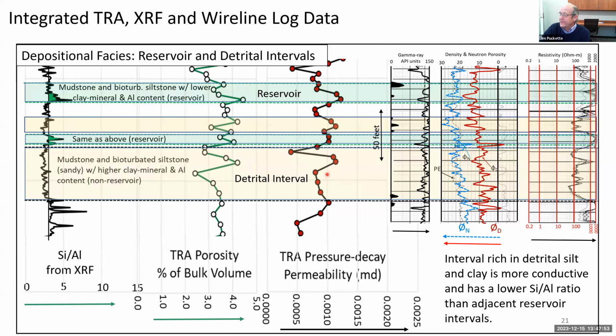And we see some pretty good porosity here at 4%. We see some pretty decent permeability in this rock. Our neutron and density curves aren't trying to really go towards each other, but they're not separating either. And our resistivity, well, in certain intervals here, it's getting up close to 1,000 ohm meters, but overall it's between 100 probably and 200, 250 ohm meters across here. It's not like our proven reservoirs where we're getting out there with that 800, 900 ohm meter rock. But I'm anxious to see if this rock will work and produce commercially.